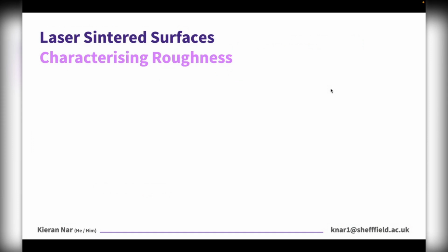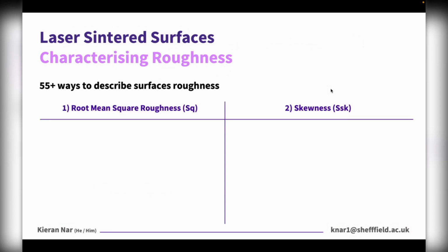Now, the first experimental package of work that I undertook when beginning my PhD was to characterize the roughness of laser sintered nylon 12 surfaces. Though when setting out to do so, I quickly discovered that there is way more to roughness than just one value. In fact, there are over 55 different ways to describe surface roughness. But the two that I determined were most apt for my work were root mean square roughness and skewness.